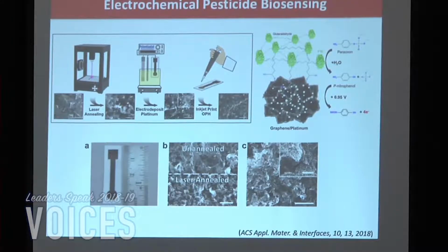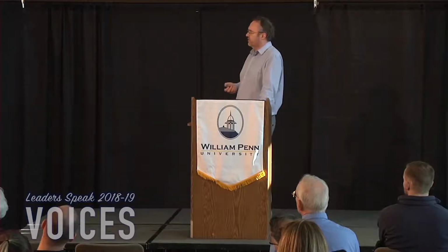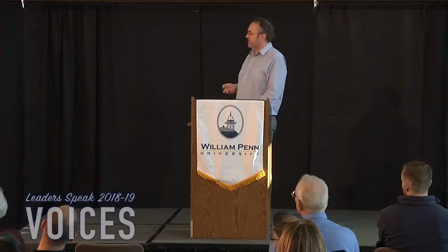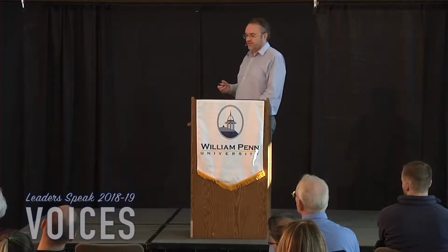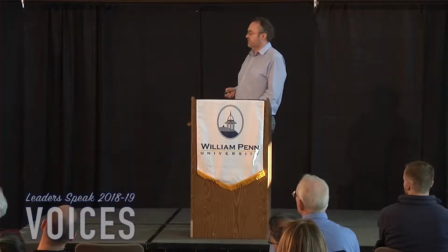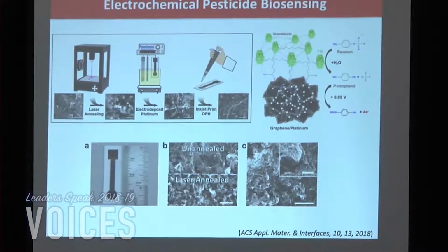And there are all different types of biorecognition agents: enzymes, antibodies, aptamers, and so forth. In this case, we are working with collaborators from the U.S. Naval Research Laboratory who made a specific enzyme that attaches to a pesticide, to a nerve agent, organophosphates. This type of enzyme can break down an organophosphate into an electroactive species, and that electroactive species can oxidize on the surface of the graphene and give us electrons that we can measure and then correlate to the concentration of pesticide in solution. So we immobilized this enzyme on that surface, and this was a graphene surface with platinum nanoparticles. We just peppered it with a few small particles, around 20 to 25 nanometers in diameter, to make it even more electrocatalytic.